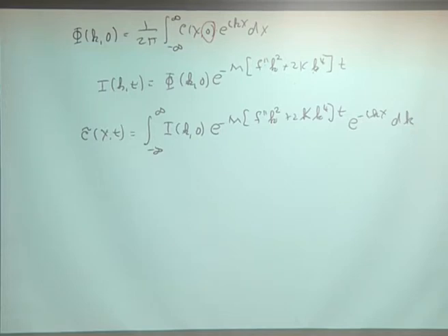I can tell you whether that wave vector k, or the Fourier transform at that wave vector k, grows or shrinks by just looking at this term here. It's independent of this. So what you want to think is that you take the Fourier transform, you get sines and cosines, and each of these sines and cosines decays or grows depending on this factor here. And they do it independently of each other.